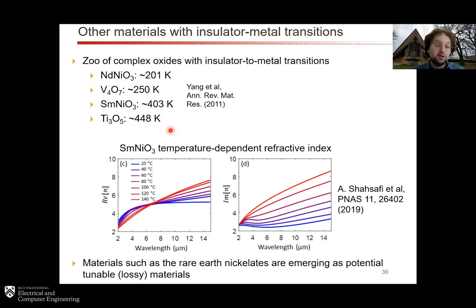So there's a zoo of materials that have not been explored for optics, as far as I know, and have not been explored for thermal emission engineering that we're very excited about. But we did start looking at one other one, which is the samarium nickel oxide, which has a phase transition at about 400 Kelvin.